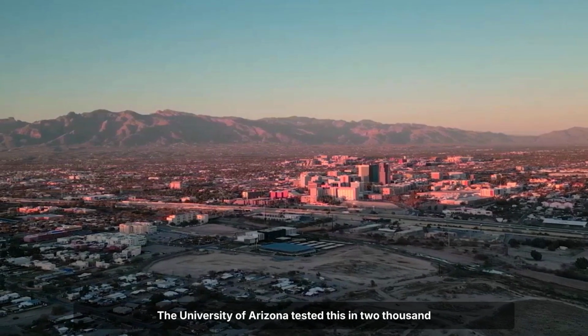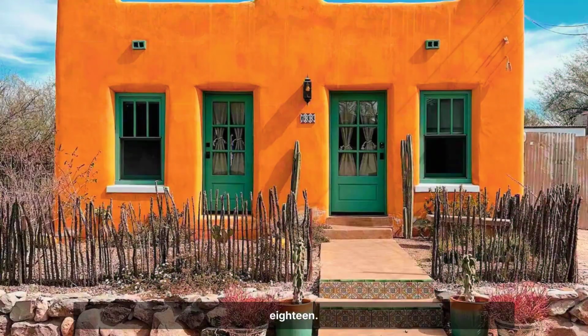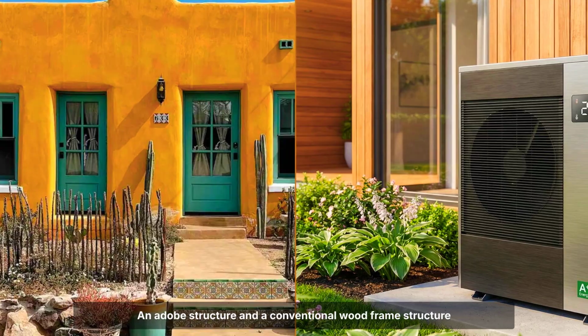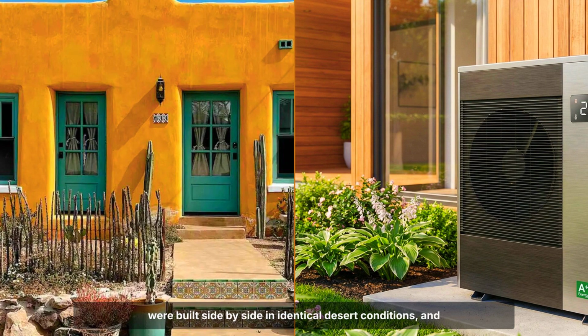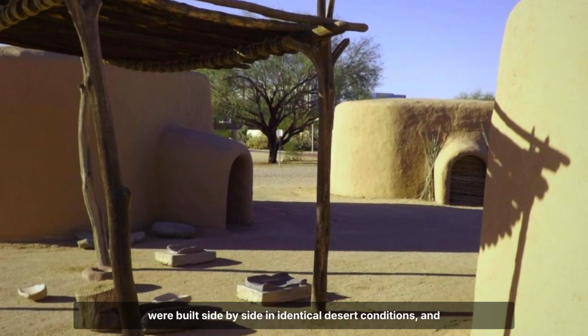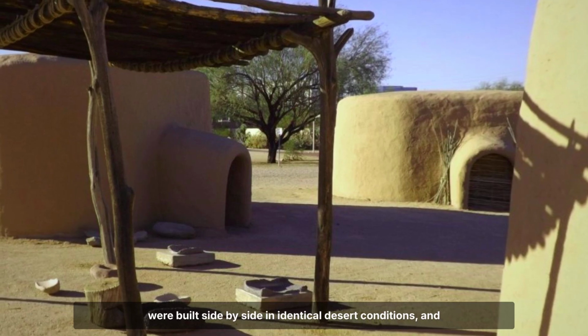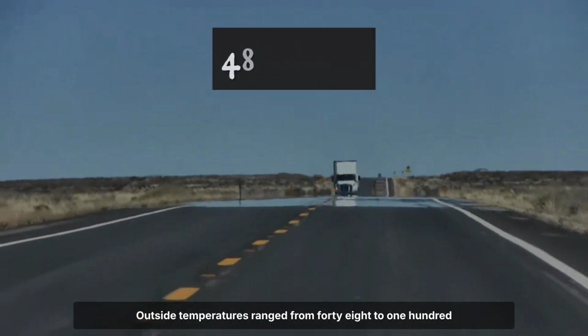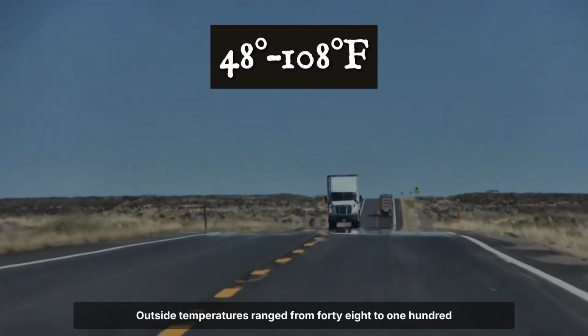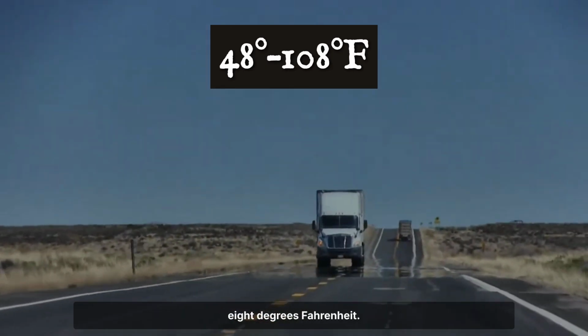The University of Arizona tested this in 2018. An adobe structure and a conventional wood frame structure were built side by side in identical desert conditions and monitored for 10 months. Outside temperatures ranged from 48 to 108 degrees Fahrenheit.